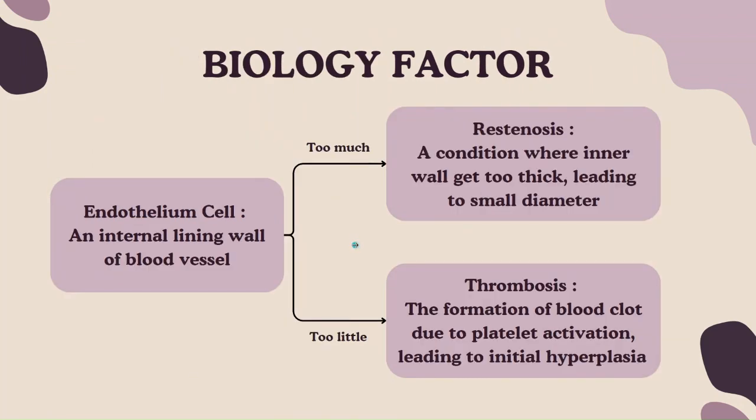So lastly is the biological factor. This part I want to discuss is the cell adhesion of the endothelium cell. This is the cell that is responsible for generating new tissue surrounding the vascular graft. If it generates too much tissue in the short term, it could cause restenosis. It is the condition where the internal diameter of the blood vessel gets too small, leading to a higher flow resistance and causing a blockage in the long run.